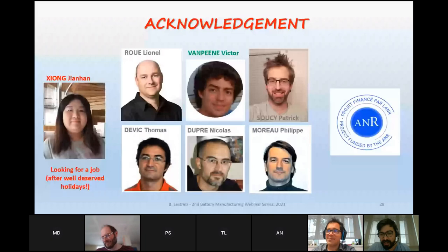Yes, of course. The next question is from Hassan Olarvi, who asks: Professor Bernard, thank you for this very interesting lecture, could you comment on the particle size of the silicon you used? So this silicon is prepared by Lionel Roue by milling. In the end, we have micrometric particles that are nanostructured, that is to say, they are made of nanoparticles of 20 to 100 nanometers. When we process the slurry, these micrometric particles are broken down into smaller particles. We can have an idea by looking at the TEM images, but they are typically 100 nanometers to 1 micrometer thick.